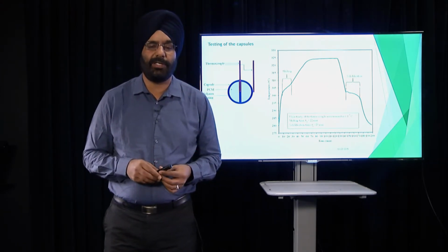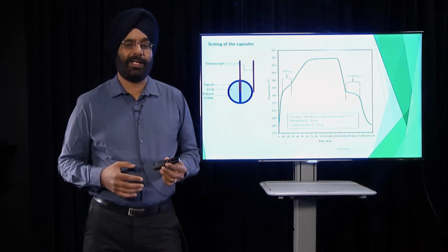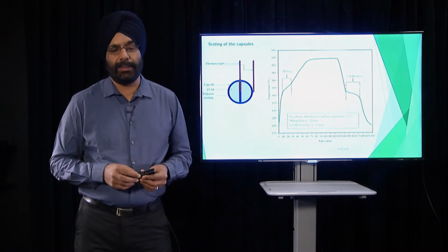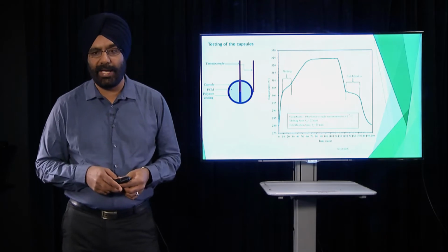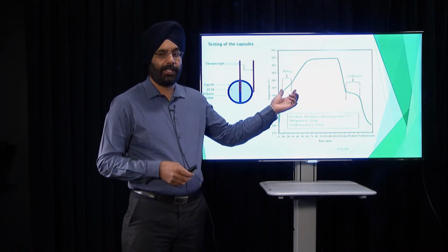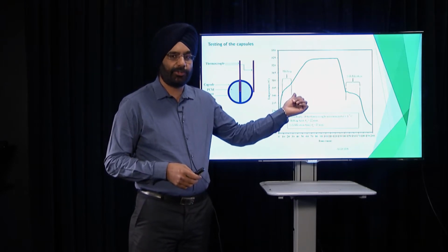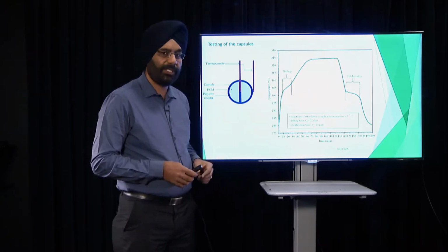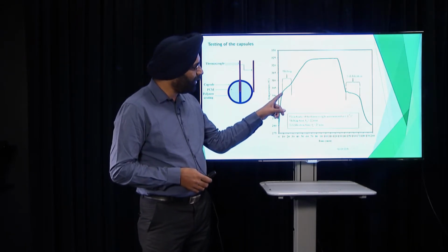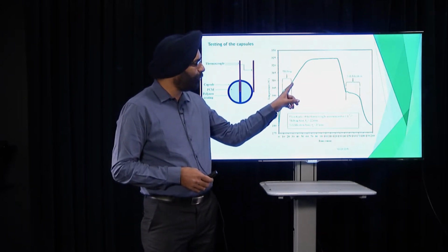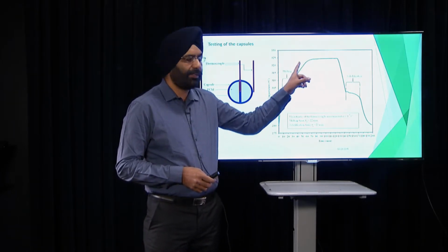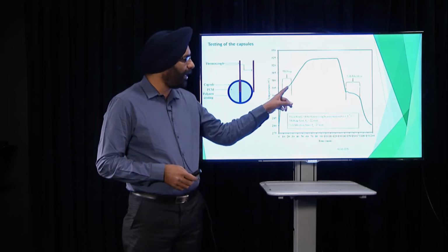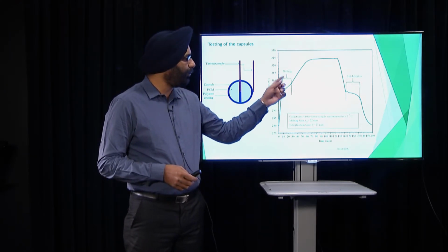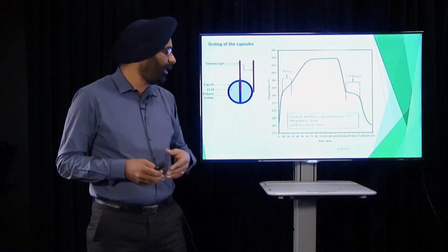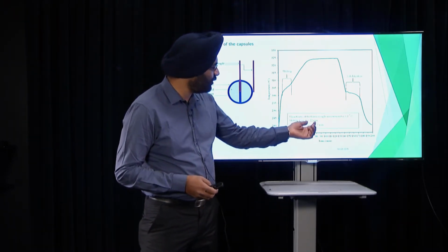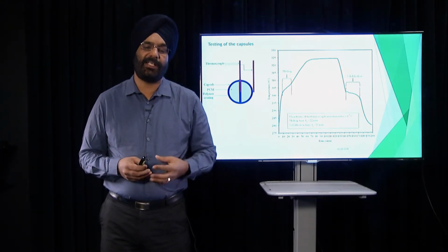So that's the other advantage of the latent heat. When that happens, we can have more useful work done from it. There's the second law of thermodynamics there. So it's better in that aspect also, that the heat is stored or heat is taken out under isothermal conditions. So we know the melting started somewhere here and it is complete at this point, because at this point again the increase in the temperature is faster than what was happening here. So this window here represents the melting, and this told us that it took around 22 minutes to melt the salt inside that capsule completely.